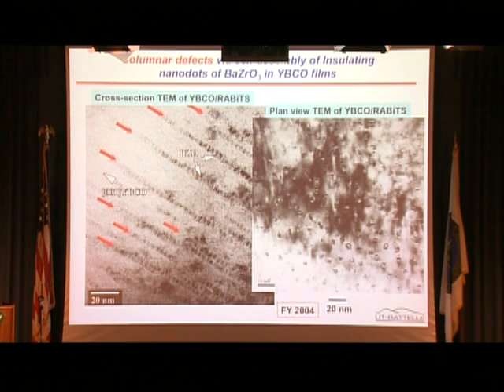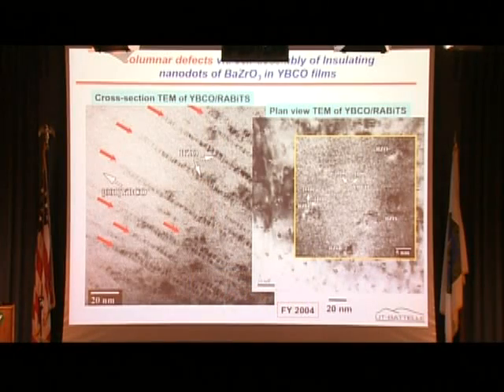So here is an example looking at cross-section into a YBCO film, where we've created these nanodots of aligned barium zirconate non-superconducting columns. And if you were to look down this way in a TEM, they would look like this. These hole-like features are barium zirconate columns. And you can see that this structure now is starting to resemble the Swiss cheese microstructure. And if you take it slightly higher in magnification, you can see that these are indeed nanoscale in dimensions and separated by nanoscale distances.